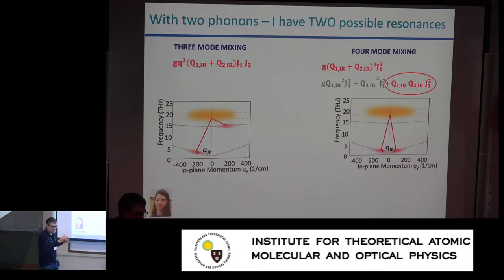So once you start peeling your onion and you look at the process, there are just a lot of details. And this turns out to be very strongly connected to what Mohammed said, that this process doesn't really explain what we were seeing, precisely because the seed of this amplification process is an incoherent noise. And so I should not have an oscillation that always looks the same. A number of things should average out to zero when I do the experimental process.